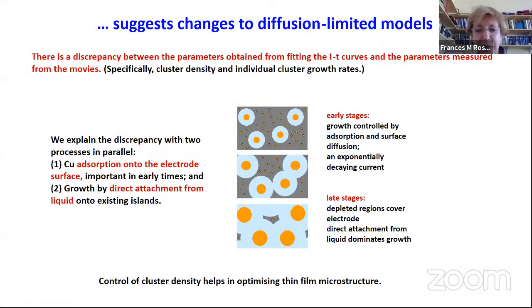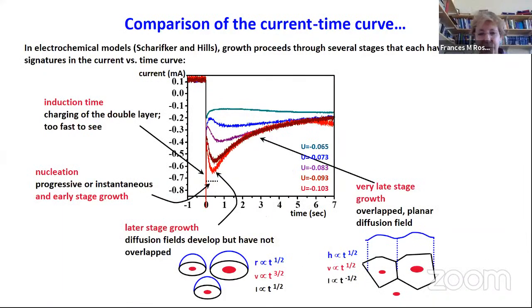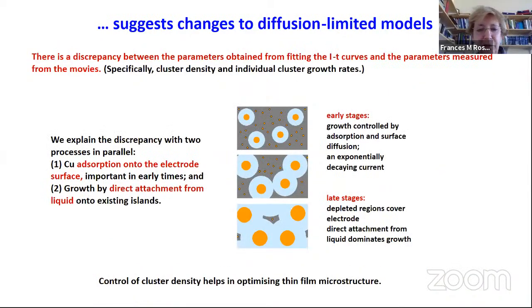And so the models work to a great extent, but there's a big discrepancy between the parameters you obtain, for example, for nucleation density, from fitting the current time transients, these ones here, and what we actually see in the movie. And so the way that this could be resolved in understanding what's going on is to say, we think that the simple model of the copper ions arriving from solution onto the existing nuclei is not complete. We have to consider two diffusion processes.